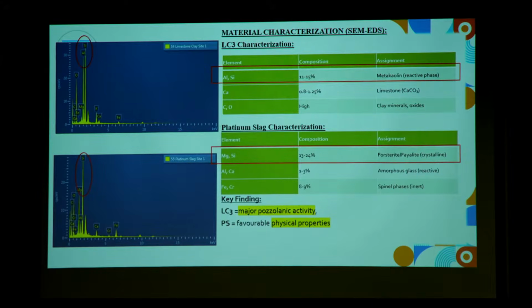Now, material characterization was key in order for us to be able to understand the results that we would obtain. The key findings here within the SEM analysis is that the limestone calcined clay, the LC3, was dominant with our metakaolin and reactive phases, resulting in major pozzolanic activity. And the platinum slag was giving off favorable physical properties, with forsterite and crystalline phases being present there.